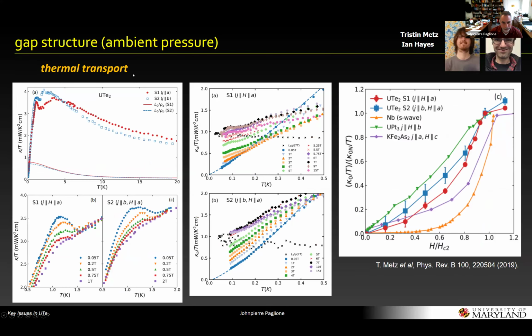So on to thermal transport, and this is another study we did early on, which suggested that the superconducting state definitely had a point node gap structure of some sort. So these are two samples. We measured heat currents along the A and B directions, and you can see that in both cases, the zero magnetic field, zero temperature extrapolated data pointed to zero, but had a rapid rise with temperature and a rapid rise with magnetic field, which was consistent with nodal excitations. This is the blue and red data here, which rise with magnetic field, unlike fully gapped superconductors such as niobium, which show classic activated behavior with magnetic field at zero temperature. So that led us to conclude that there's a point node gap structure, at least in the first generation